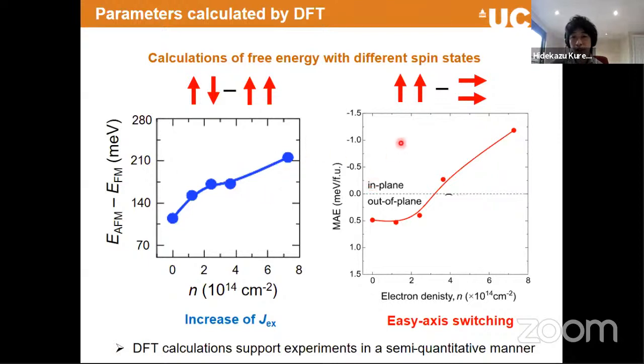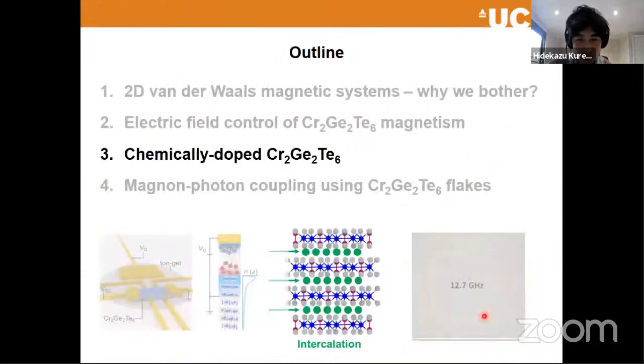Also, in DFT, what we can do is that in a ferro state, we simply rotate the moment 90 degrees, and that can tell us the difference between the energy of these states, i.e., the magnetic anisotropy. And nicely, when we look at this energy difference, we can also see the sign switch of this value, meaning that the easy axis can be different for out of plane and in plane, promoted by the carrier doping. Okay, so that's what I will show from the electric field component.